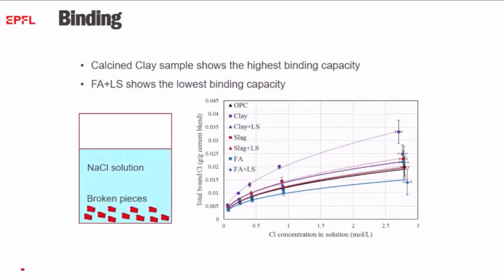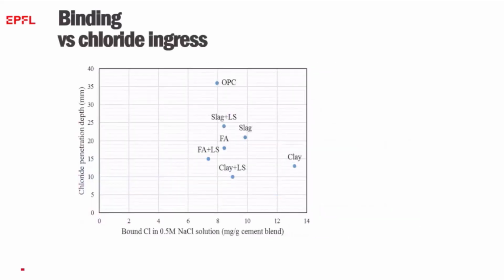Many people say, well, it's all down to binding, and binding's rather complex because, yes, you form more carboaluminates which combine chlorides, but on the counterpart, you've got less CSH, so that's less chlorides. So if you look at the concentration we have in seawater, which is really what we're talking about, you see most of these blends don't have much difference in their binding capacity. The one that has the highest was just the calcined clay on its own in the binary blend, but in fact we see that that didn't have the best performance.